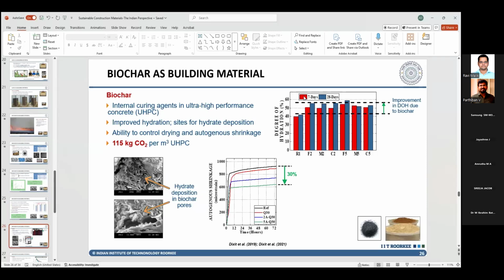Now, a very peculiar case is UHPC. UHPC is ultra high performance concrete. These are a very special type of concrete that have strength above 120 megapascal. So the majority of my PhD research was on UHPC, and I used biochar to see if that internal curing effect can be obtained in these concretes also, because for UHPC external curing works very ineffectively. In the first day itself, the degree of hydration of the UHPC becomes similar to what a 28-day-old normal concrete would be. So in a 28-day normal concrete, if you try to cure externally by putting it in the water tank, it will not work. So the same is the case with UHPC. So we try to cure it internally.